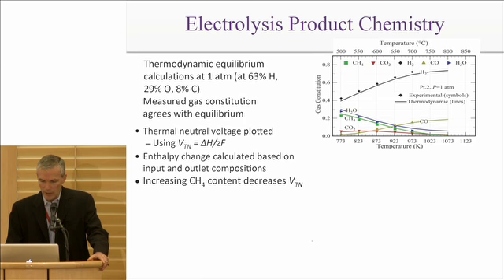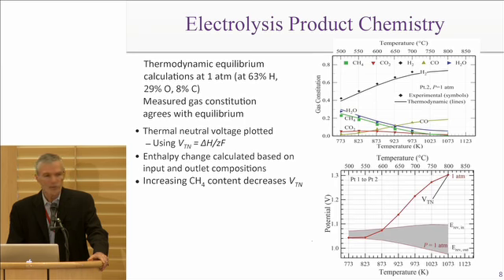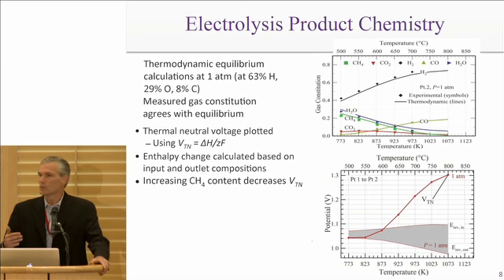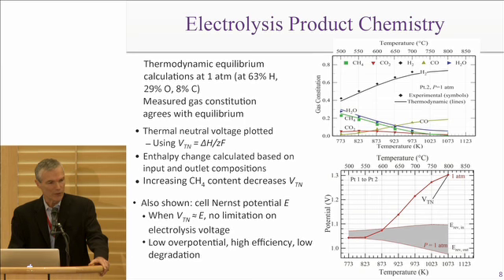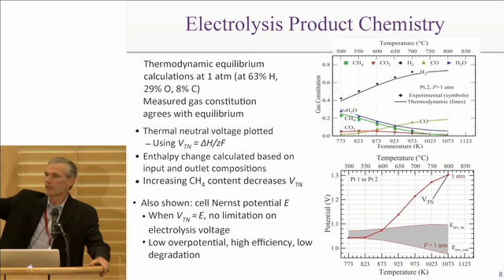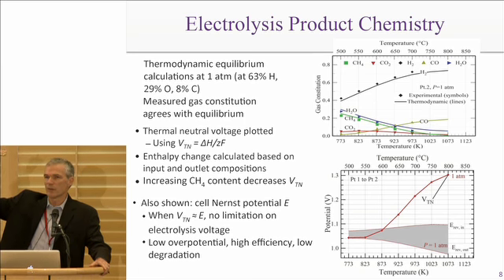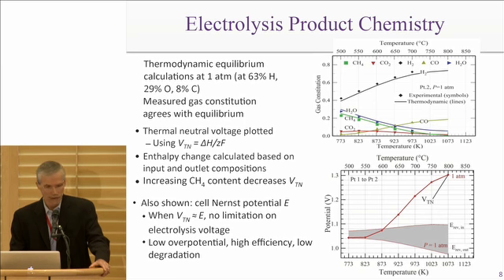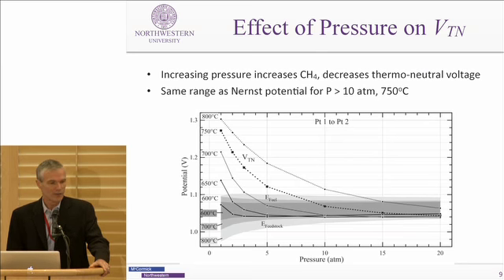Okay? And so based on knowing what these compositions are, we can go back, calculate new delta H's for the reactions. Okay, so these are now different because we have different products. And it turns out that if we do that, we see that the thermal neutral voltage at the high operating temperature, again, is fairly high, 1.3 volts. But if we drop the temperature down to, say, 600 degrees centigrade, where we're starting to get these other products, we see that this thermal neutral voltage is dropping down to around 1.1 volts. Right into this range here, the gray area is where the Nernst potential for the cell is. So that means we've eliminated this limitation of needing to have the electrolysis voltage as a very high voltage to maintain the cell operating temperature. Okay? And that was going to allow us to get a high efficiency in this process.